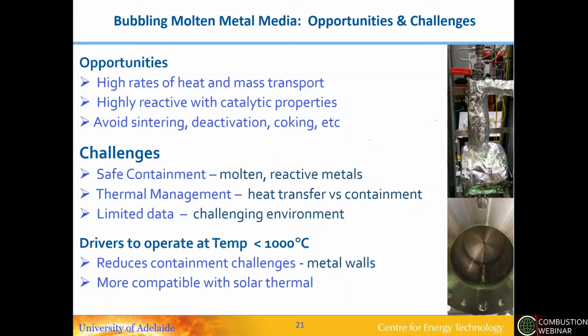So the work that's been done to date is typically involving reactions at temperatures of above about 1,000 degrees. So one of the things that we've been working on is to try and take the temperature to below 1,000 degrees, which will reduce the containment challenges, because it means that the reactor can be contained within more conventional metallic materials, albeit potentially with some lining, but it's much safer. But also it's more compatible with the solar thermal temperature. So these are some of the reactors in our laboratory that we've been developing.